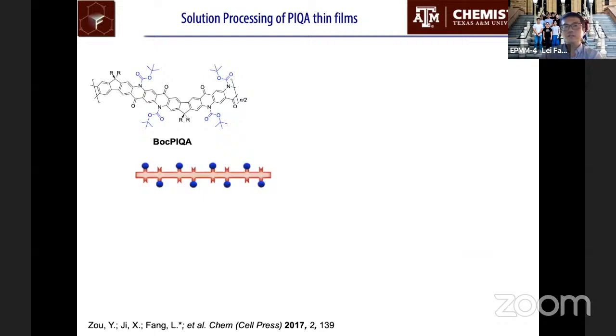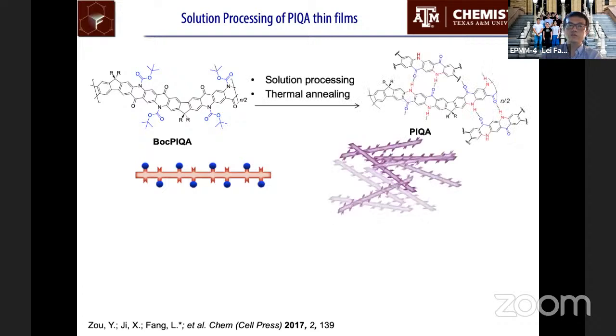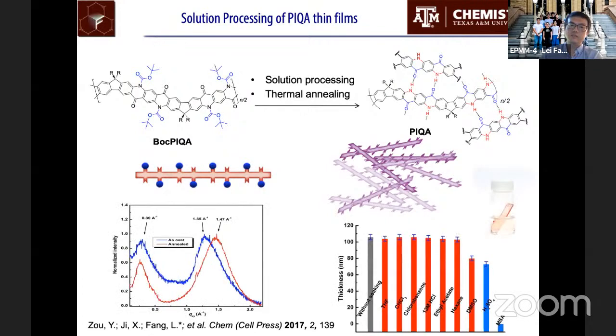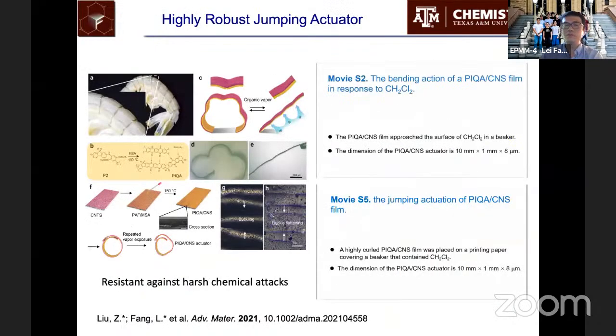And then once you cast the thin film, we could utilize the reversible reaction of Boc cleavage to regenerate the hydrogen bond and then get a highly solvent-resistant and chemical-resistant thin film. So basically we could fabricate a thin film with very strong solvent resistance by using solution processing techniques. This allows us to explore some very interesting applications.